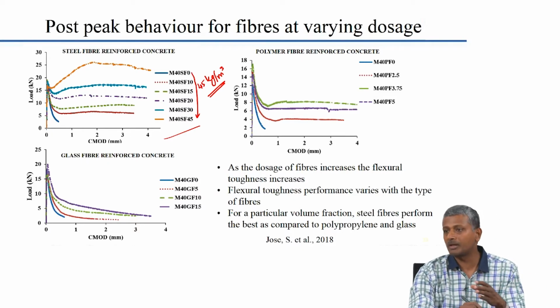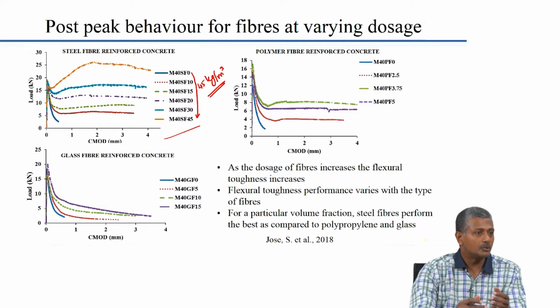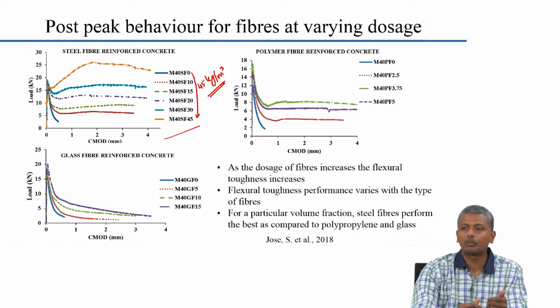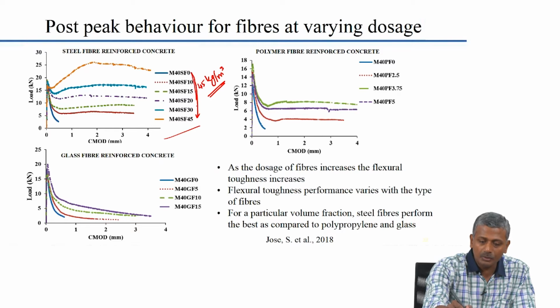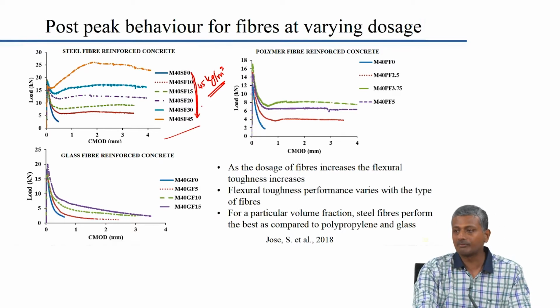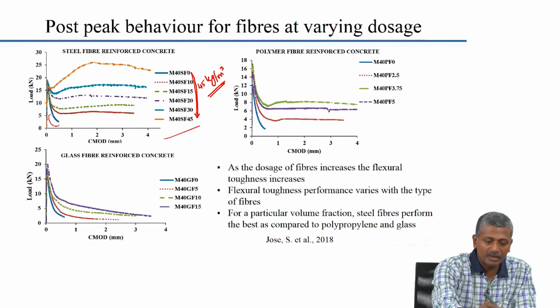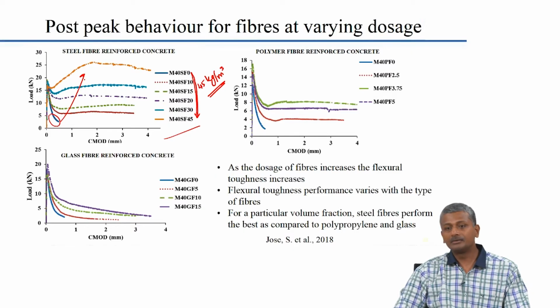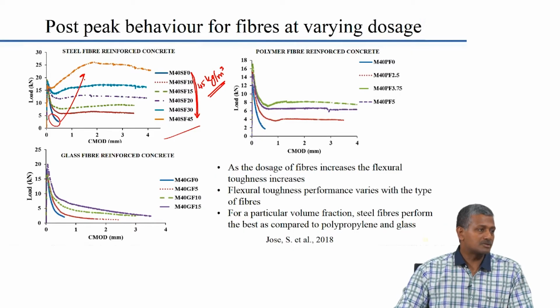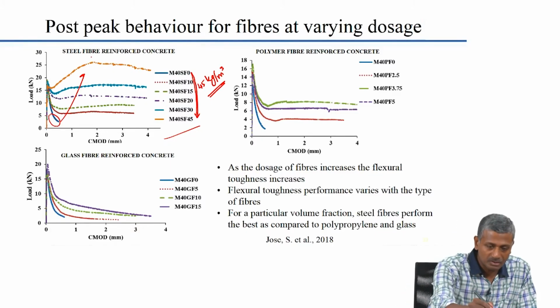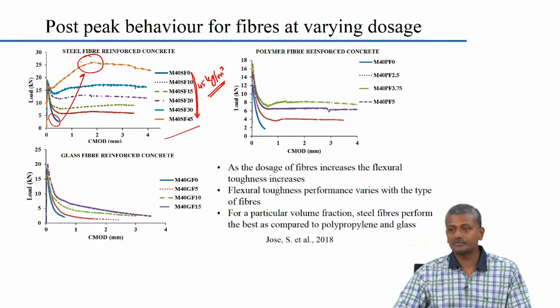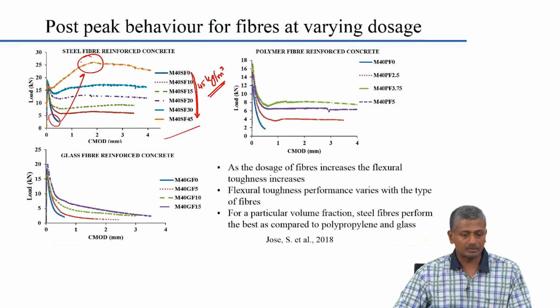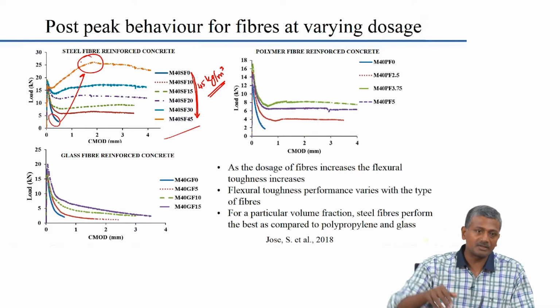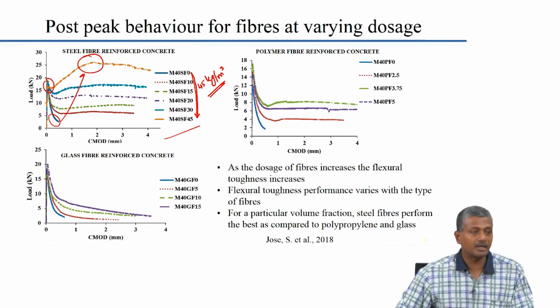Okay. That is probably going to be a high loading, but at the lower end, for example, when you want pavements and other such structural components, you can actually have much lower loading like 0.25% or 0.15%. That is why this range of dosages was attempted in the study from 0 to 45 kilogram per cubic meter, and you can obviously see for the plain concrete there is not much deformation, but as the fiber dosage increases, the extent of ductility that you can get from the system gets enhanced significantly, and actually at the very high dosage you are even observing some strain hardening cementitious behavior that causes your stress to actually go up even after that initial deformation or kink happens in the system.